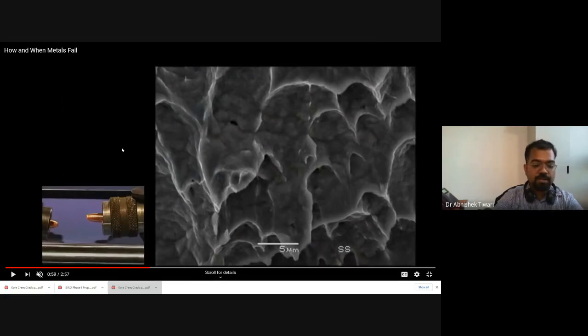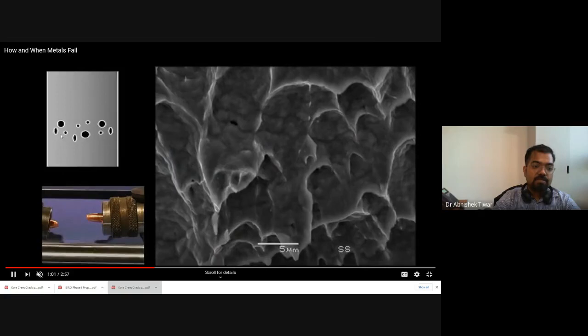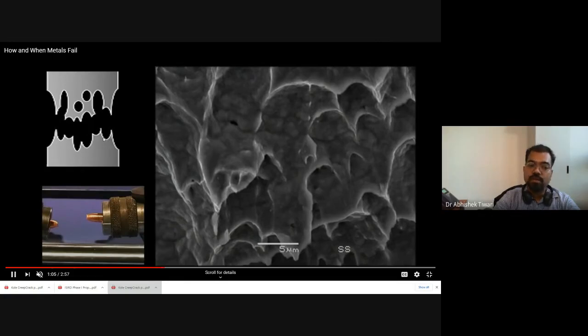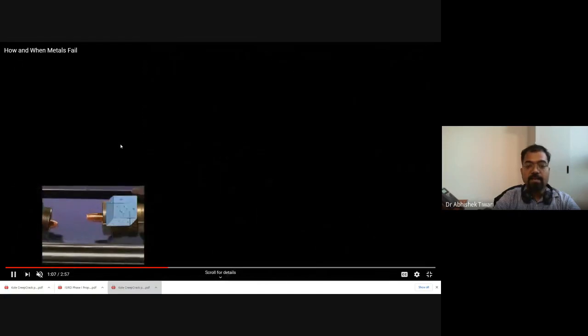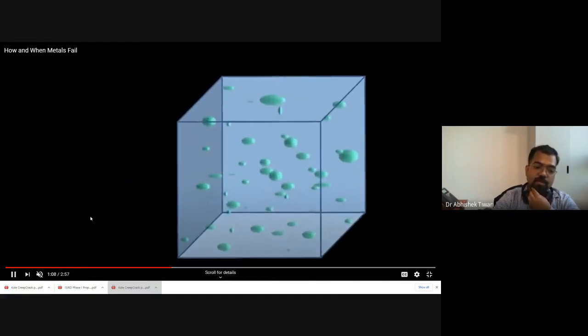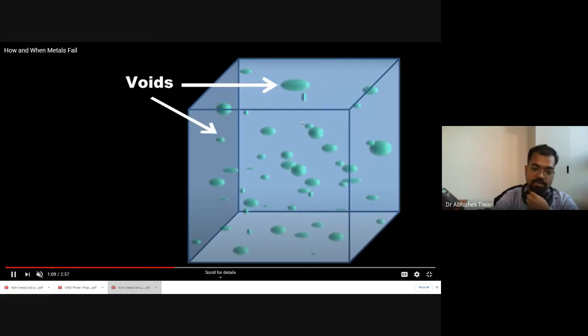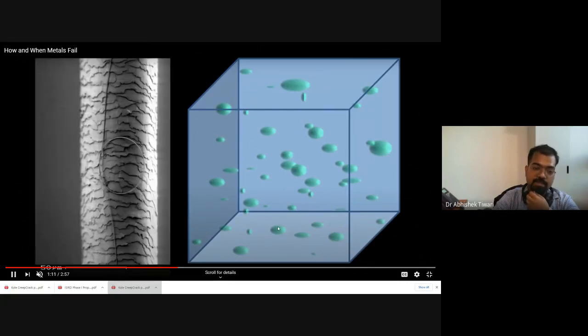So in this video, what they explain is a very nice idea in computational, numerical simulation: how can you find out what is happening in the material in reality by doing some mathematics behind it. The idea is very simple. What this person is proposing is that instead of taking all these voids in one go, you can take a small piece of the material where you assume that there is only one void. And then you find out the properties. So you take a small volume, so you will have a lot of voids in this area once the damage has started.